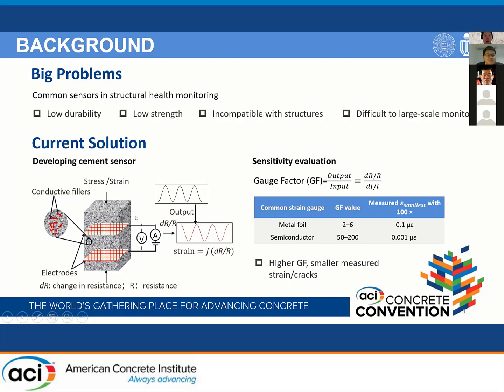For this type of cement sensor, the sensitivity is usually evaluated by gauge factor. Gauge factor is a very important parameter for the cement sensor because generally the higher the gauge factor, the smaller the strain or cracks that the sensor can measure. We can see this from this table.